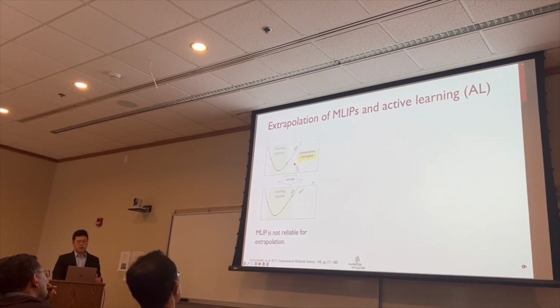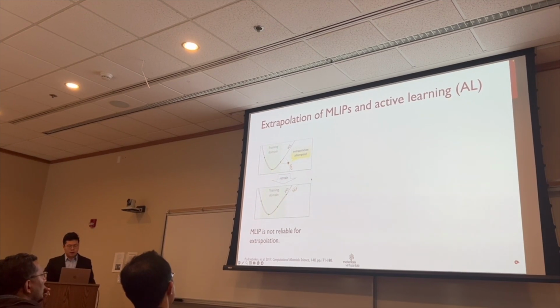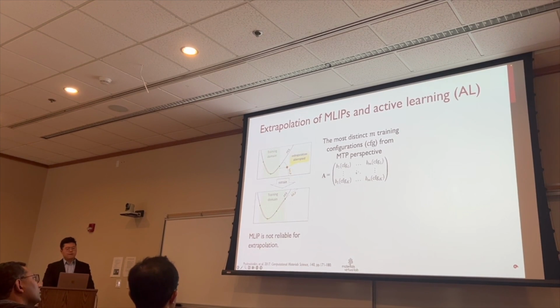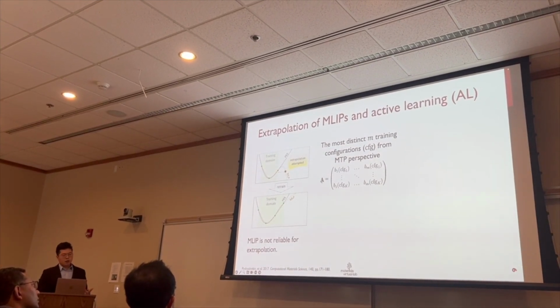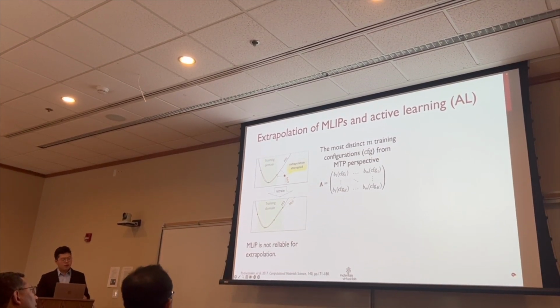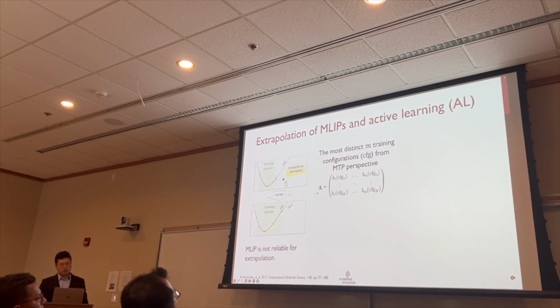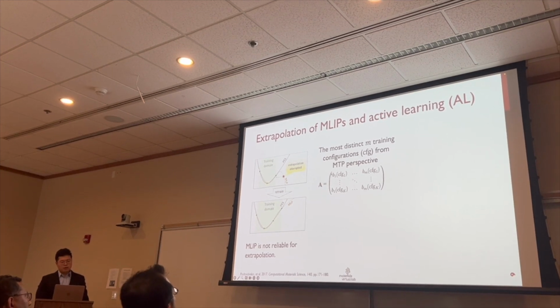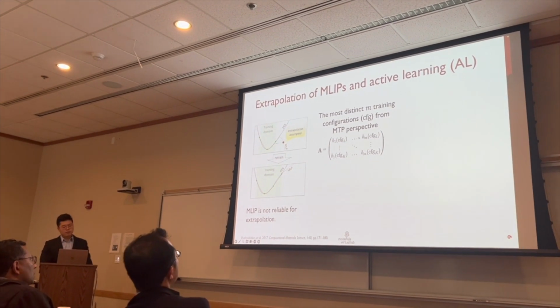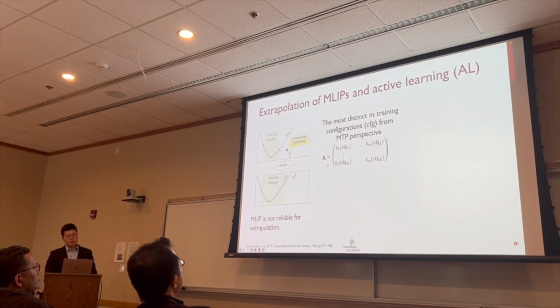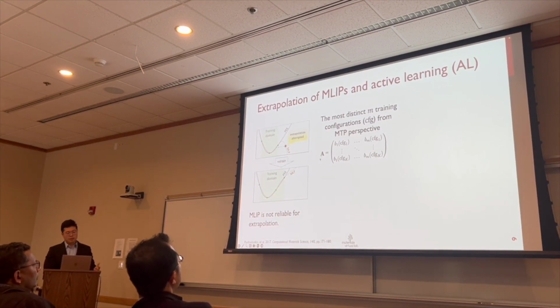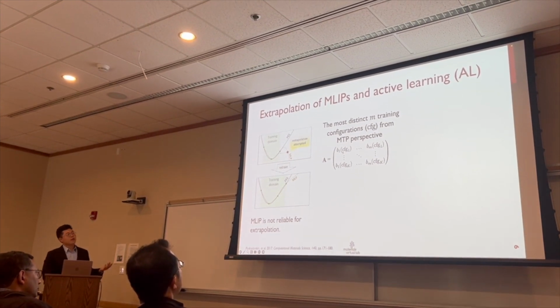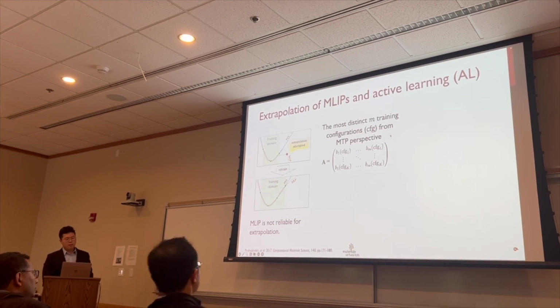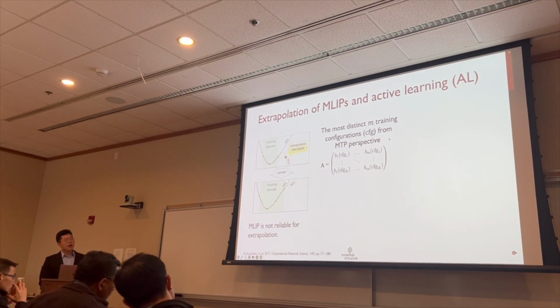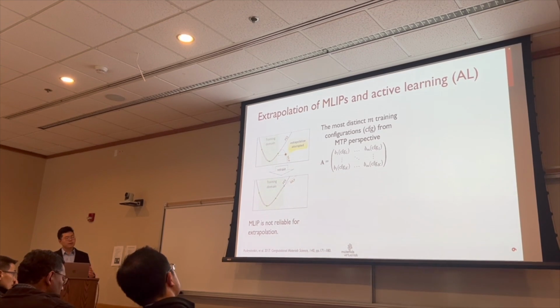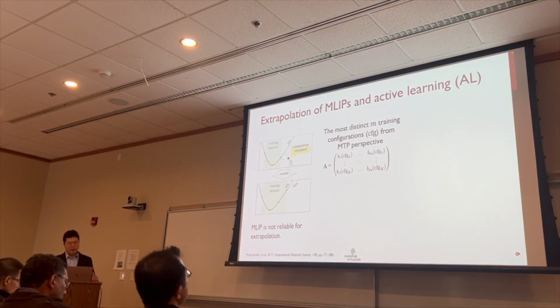And to detect this extrapolation behavior, the moment tensor potential developers actually invented a way to quantify this extrapolation. In their method, we first need to find this matrix A, which represents the most distinct M training structures from the whole training set. This matrix A is constructed as an M times M matrix in a way that each row represents the basis functions of one configuration in the training set, and there are M configurations, so that the determinant of this matrix A is maximized. In this way, these M structures represent the most distinct structures in the training set. And by comparing any new configuration to this training set, we can know if the new structure tends to have extrapolation behavior or not by the MTP.